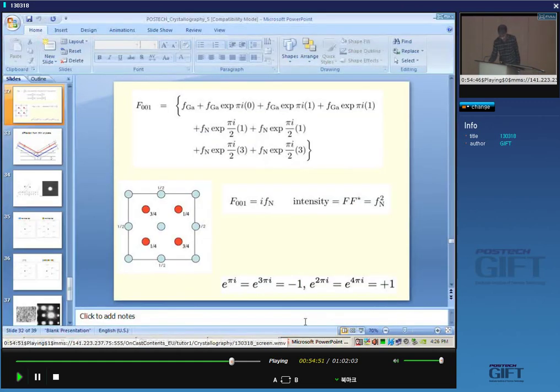So when I do F F star, I get the intensity is really coming only from the nitrogen atoms for the 001 planes, proportional to the scattering power of the nitrogen atoms. Okay? So whenever we get a complex number, you just multiply it by its conjugate and you get the intensity as opposed to the amplitude. So F itself can be complex, it can be a negative number, but F F star will always be a real number.